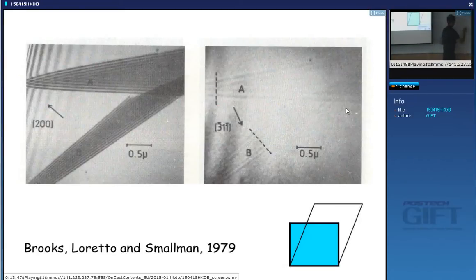So if I put my stacking fault in here, then the intensity here is different from the intensity here. Yeah? So you get bright and dark fringes if the fault is inclined. So that is simply what we call depth fringes. Right? Similarly, if you have a dislocation which is inclined, you'll get bright, dark, bright, dark, bright, dark regions on the dislocation line. Those are not precipitates, those are just the fact that the dislocation is inclined.